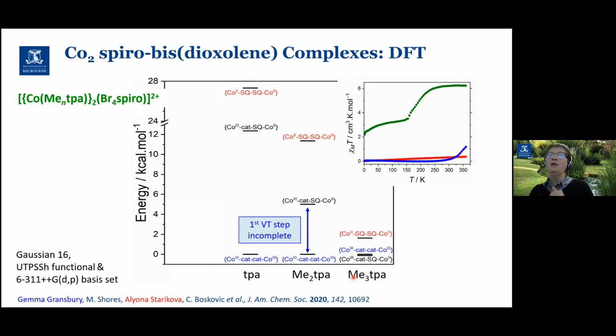Then when we go to the trimethyl TPA, now the cobalt-2 containing forms have actually come down so far in energy that the mixed valent state is actually the lowest in energy. And then the cobalt-2 semiquinone at both halves of the dimer is again quite close in energy and certainly at an accessible energy. So in that case, we actually see what we call that partial VT transition, where we're seeing the second half of the dimer transitioning as if the first half already had. So that's beautifully in agreement with our experimental data.